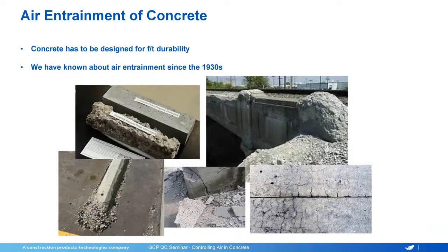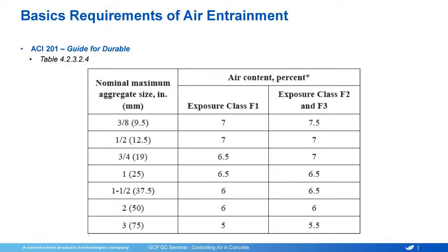This is just some really bad pictures of freeze thaw. Now, you will occasionally see something like this cracking in the bottom right hand, but mostly what we see is the concrete starting to deteriorate. And usually that's on the surface, and these are some freeze thaw beams. That one obviously is failing, and the other one has passed. And if you're not familiar with the testing for this, it's ASTM C666, and you can look that up. Again, air entrainment's been around since the 1930s, discovered accidentally by a forerunner to the GCP business in Cambridge, Mass.